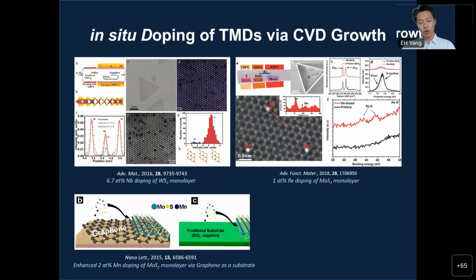So we looked into these doping issues because we were interested in these alloys. We depicted three papers here on this doping, published in 2016, 2018, in Advanced Materials and Nano Letters, on niobium doping on tungsten disulfide monolayers, and rhenium doping and manganese. Especially this manganese doping of molybdenum disulfide monolayer was predicted by theory to give room temperature ferromagnetism. Unfortunately, none of these works showed any ferromagnetism.